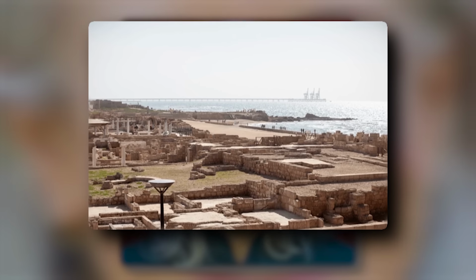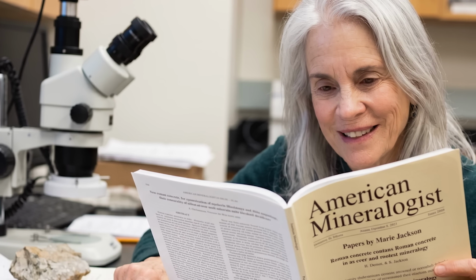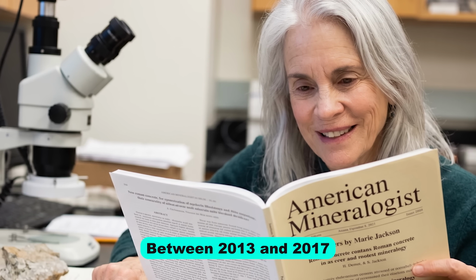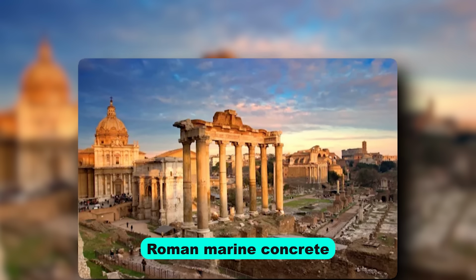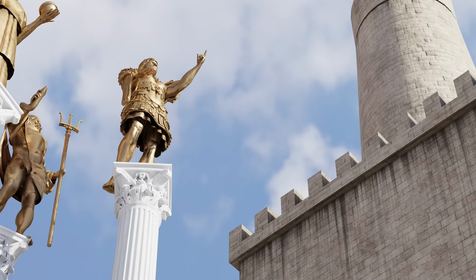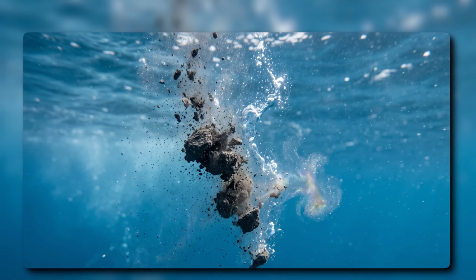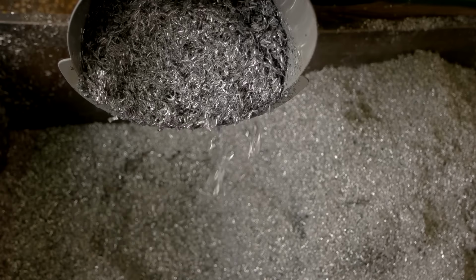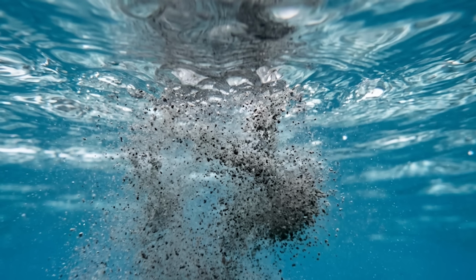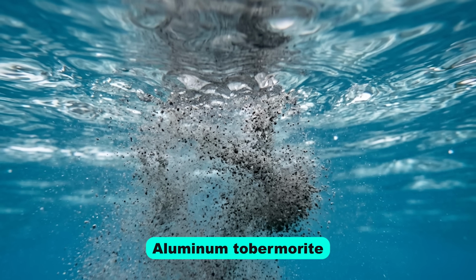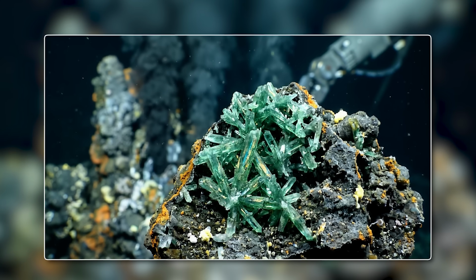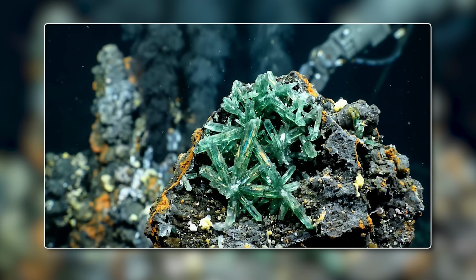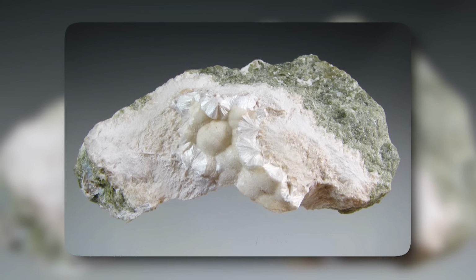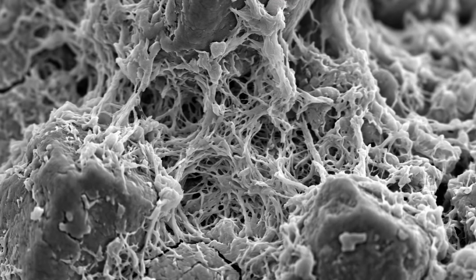Marie Jackson, a geologist at the University of Utah, spent a decade sampling those Caesarea piers. Her papers in American Mineralogist, between 2013 and 2017, traced what happens inside Roman marine concrete after it cures. Two things in sequence. First, the seawater dissolves trace elements out of the volcanic ash: aluminum, silicon, magnesium. Those elements precipitate inside the concrete matrix as aluminous tobermorite, a rare crystalline mineral geologists otherwise only find in hydrothermal vents. The tobermorite crystals interlock with each other and with the existing calcium silicate hydrate gel.